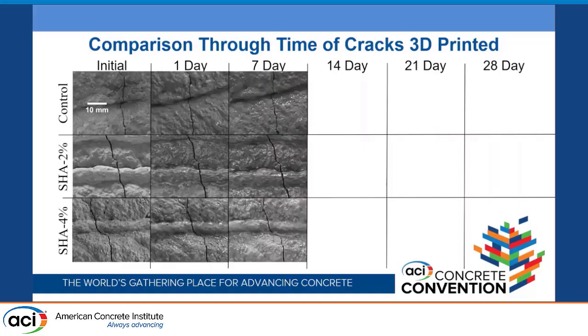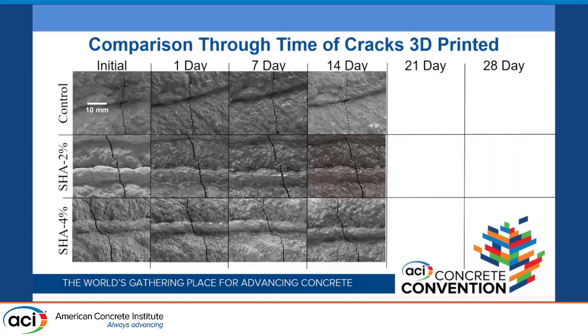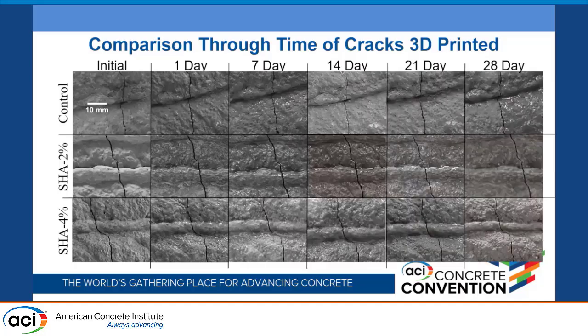Didn't see any self-healing through 7 days, got a little bit concerned. Didn't see any through 14, got very concerned. At 21, very nervous. At 28, still didn't see anything. And I thought I was going to have to redo this testing, and then I moved our samples, and I noticed—